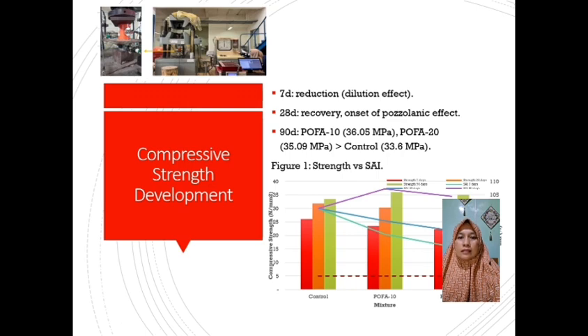The control mixture has 33.6 MPa, and then 10% POFA has 36.05 MPa, and then 20% POFA has 35.09 MPa. This improvement reflects the secondary C-S-H formation resulting from pozzolanic reactions, confirming the long-term strength potential of sieved